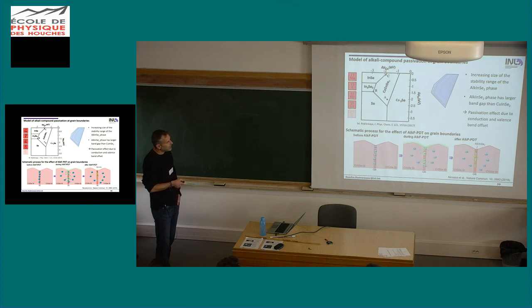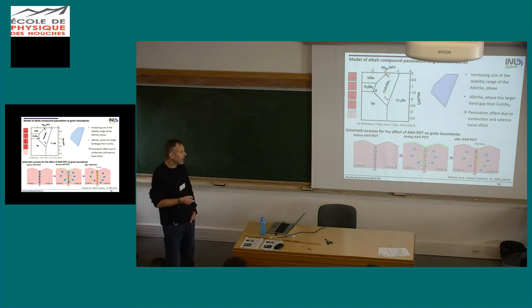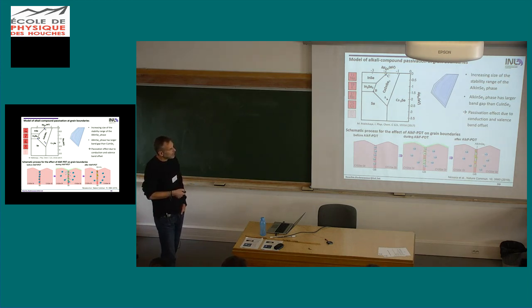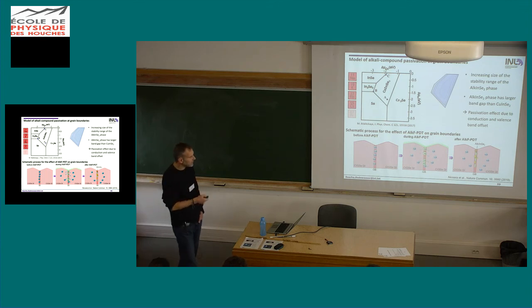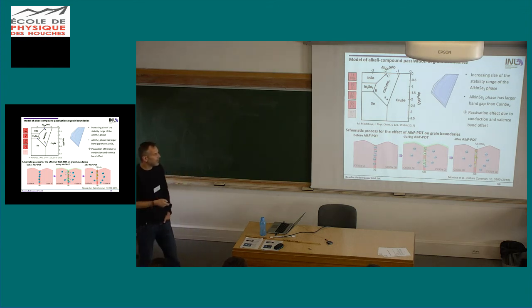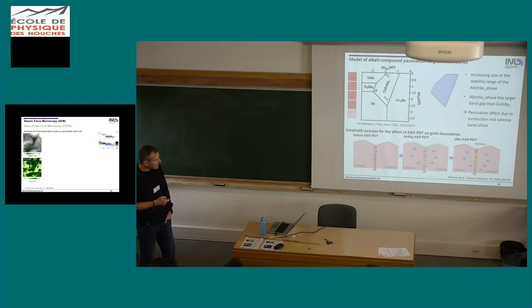So before alkali treatment, you have a lot of sodium that comes from the glass in these samples. But then when you're doing the alkali fluoride PDT, this sodium is displaced by the heavier alkali into the grains, where it then leads, and we saw this also yesterday, to a higher doping level. So this part explains why the doping level changes due to the heavy alkali treatment. And then after the alkali fluoride PDT, we get the formation of these alkali indium selenide phases. They are not complete. The concentration of the alkali elements is not large enough to make a full phase there, but there is some contribution of this wide band gap phase sitting at the grain boundary.